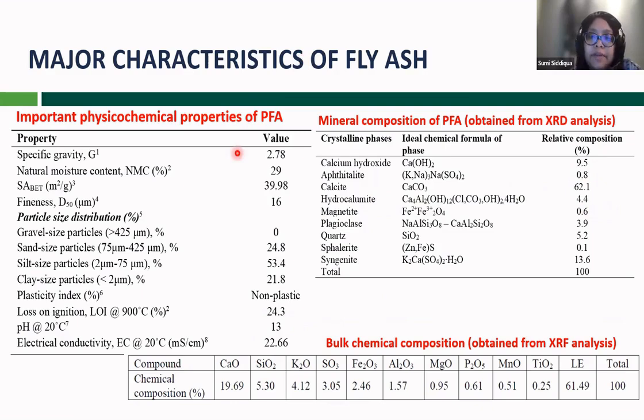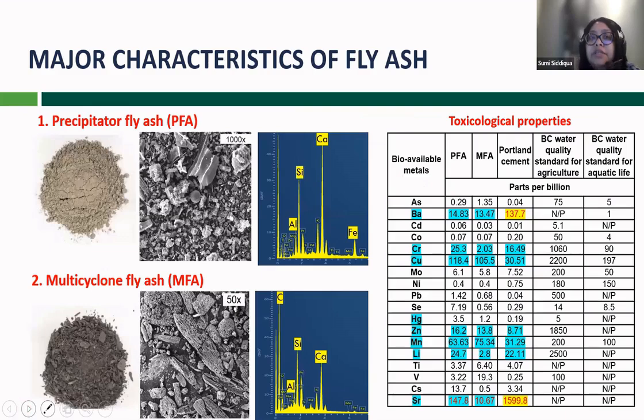material. And now by looking into the XRF analysis, then we looked into the bulk chemical composition. Again, we saw that the calcium oxide, silicon dioxide, those are the higher in percentage. However, there are some light elements, which are very high. It was not possible to identify what are those elements, but it is part of the light elements under the XRF analysis. So this whole characterization of the fly ash, and the fly ash that I'm talking about is the pulp mill fly ash. We understand what are the properties we are dealing with, and then we looked into that in terms of the microstructure.